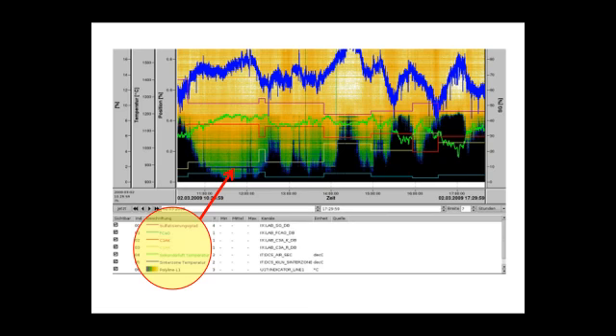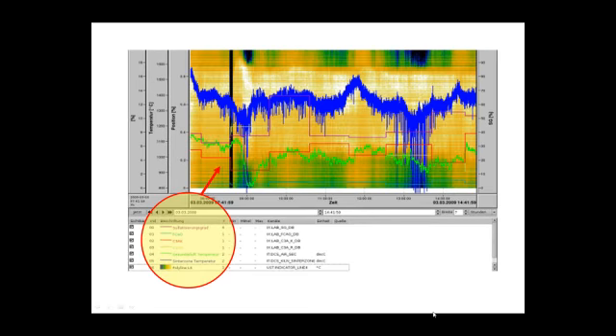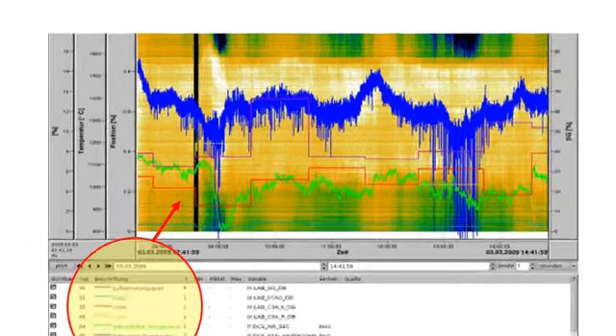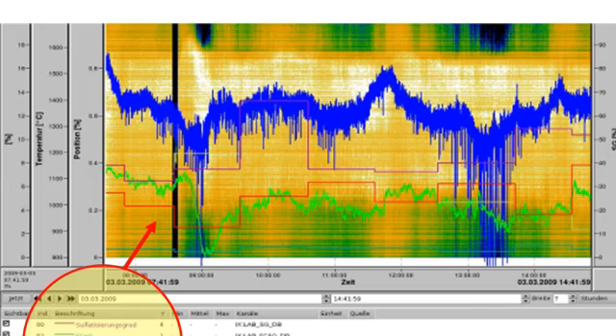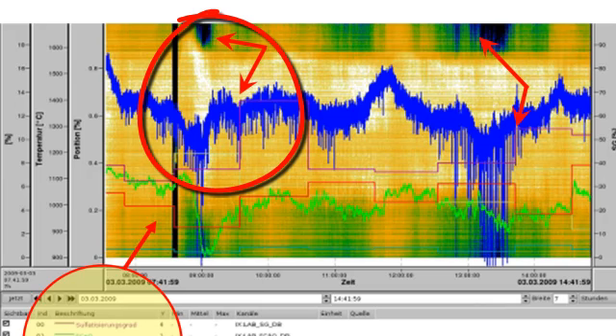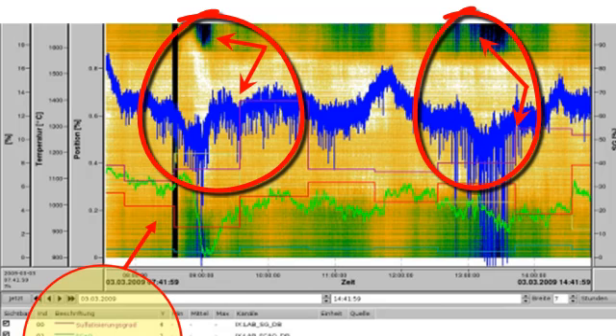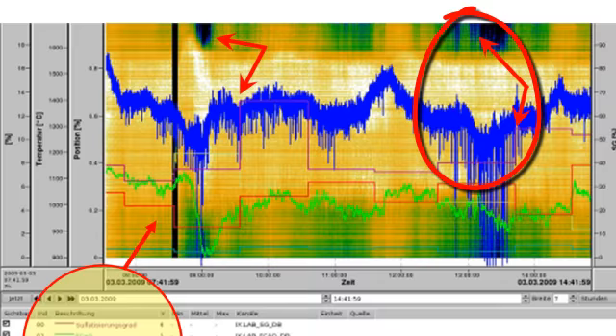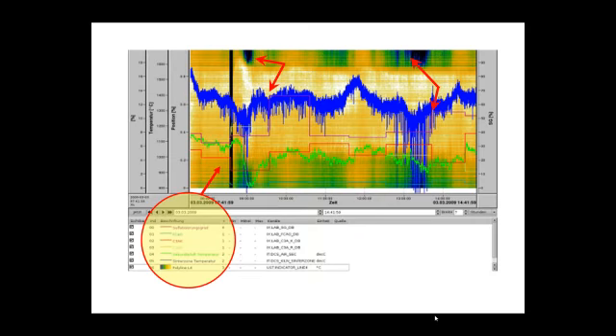This recording over 7 hours shows clear correlations of the flame diameter, sintering zone temperature, and secondary air temperature to the laboratory values free lime, C3A cubic and C3A orthorhombic. Very small changes in the flame diameter or only on the top of the flame have radical effects on the clinker quality. The changes in flame diameter clearly correlate with the jumps in the purple line indicating the sulfation degree.